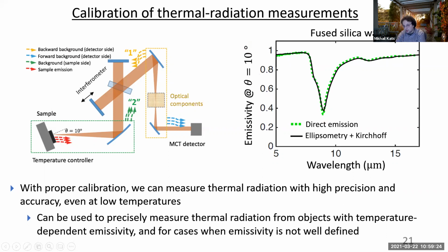So we did spectroscopic ellipsometry with our mid-infrared ellipsometers and applied Kirchhoff's law and found that the two curves lie on top of each other. There's pretty much no error bars that are visible. And so essentially, we can use this to obtain very accurate and very precise measurements of thermal radiation from various objects.